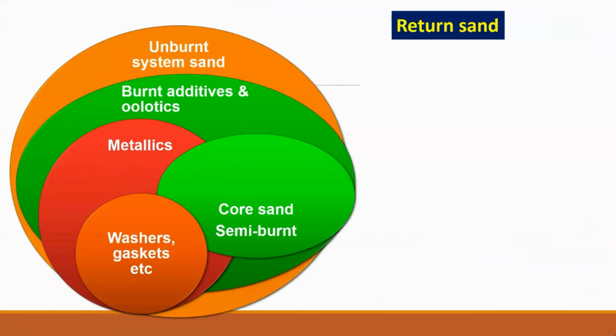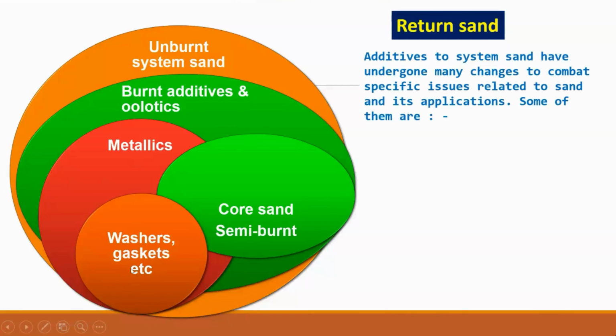So look at the returned sand again. So these are the constituents of the returned sand. You have a large part of it is the unburnt system sand. Then you have burnt additives and oolitics. I'll talk about oolitics soon. Then you have some metallic contents, which are part of the casting, which are spillages, fins, vents, and things like that. Then you have core sand, semi-burnt. The core collapses. Sometimes it remains as lumps, and then you can take it away above the shakeout. Some are crumbling and then falling into the grill. Washers, gaskets, which are part of the molding system.